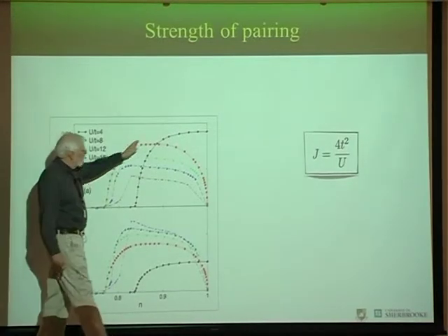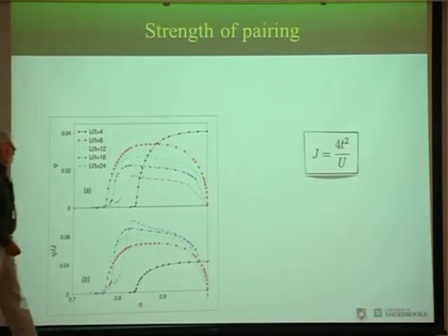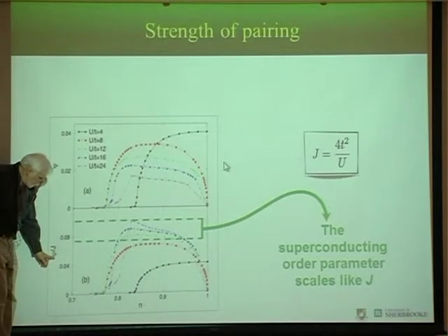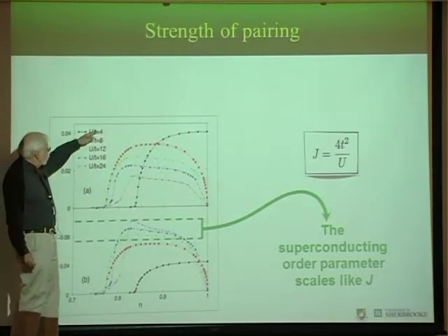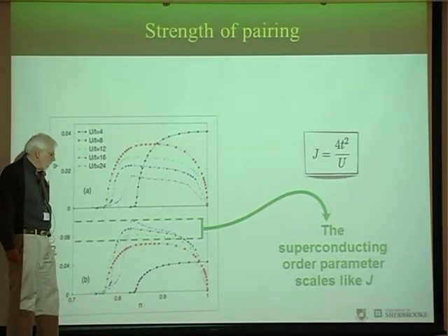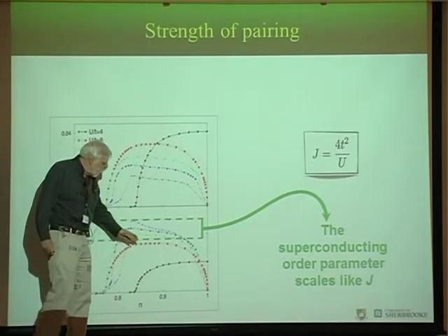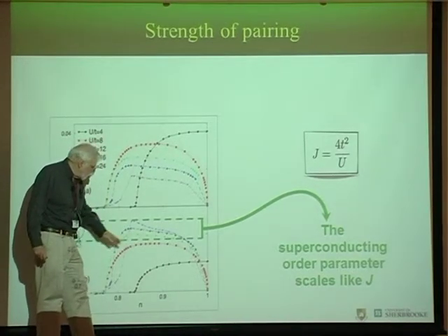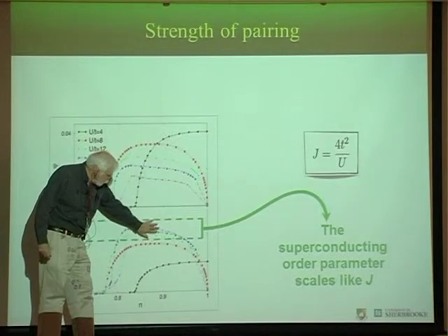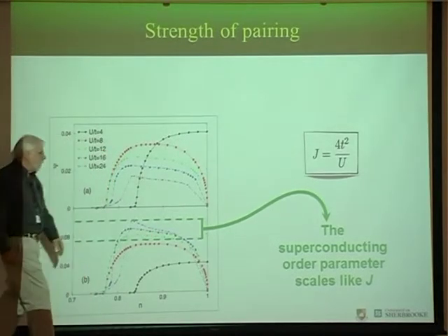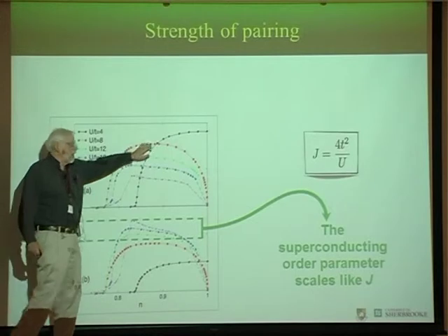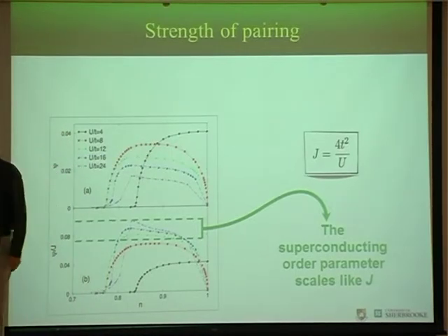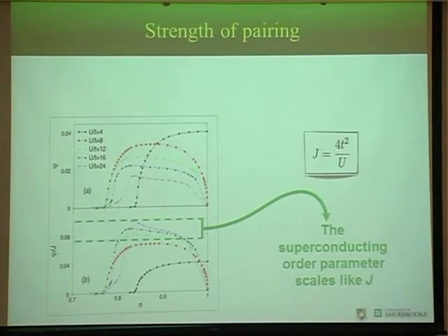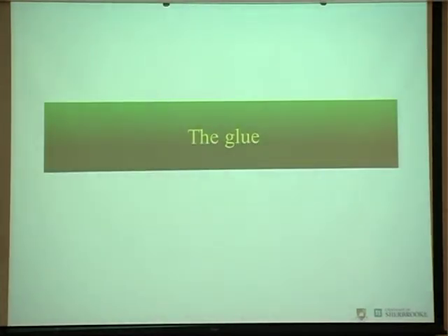If you are in the strongly correlated case, in other words, the system is a Mott insulator at half filling, you have this dome shape for the order parameter, and you can check that if you divide the order parameter by J, as U gets larger and the Heisenberg Hamiltonian, or t-J Hamiltonian in this case, becomes better, you see that the order parameter scales like J. So the optimal value for superconductivity is when you're close to the Mott transition. Yes?